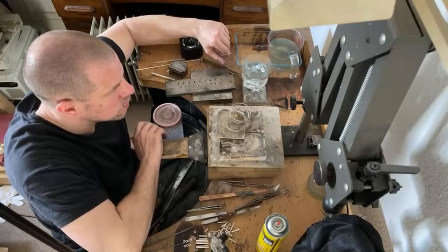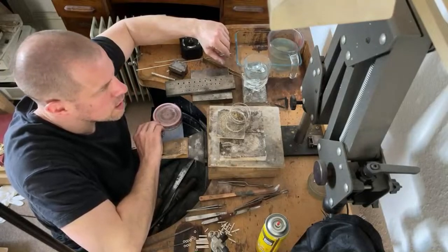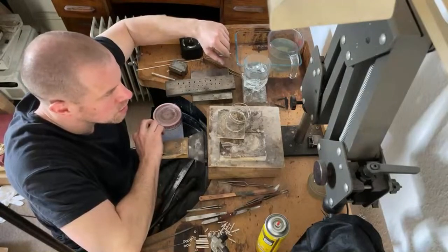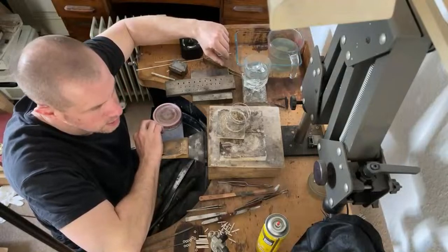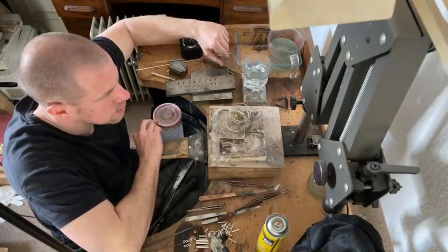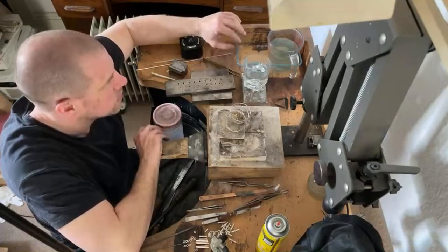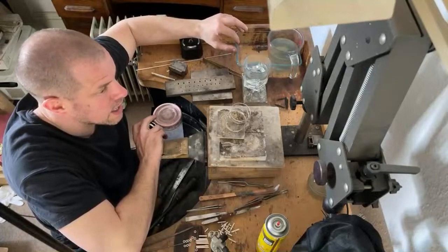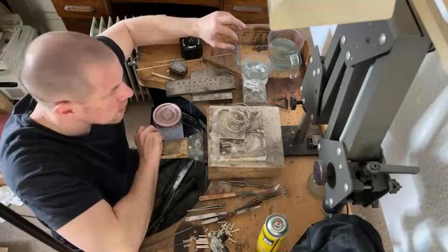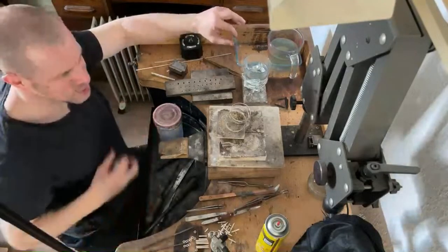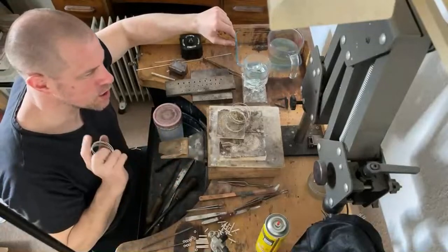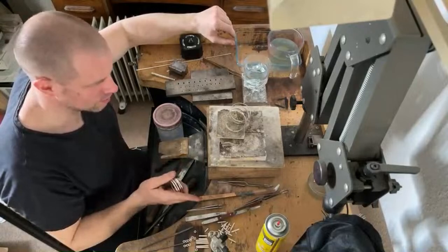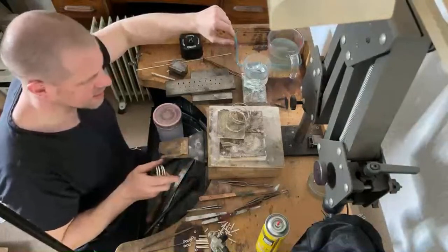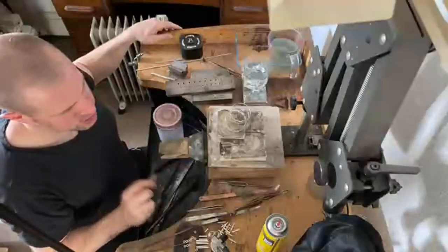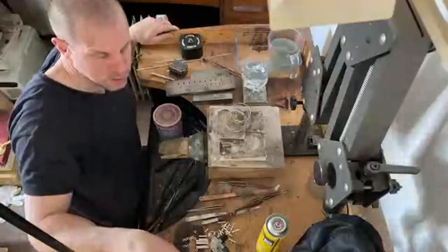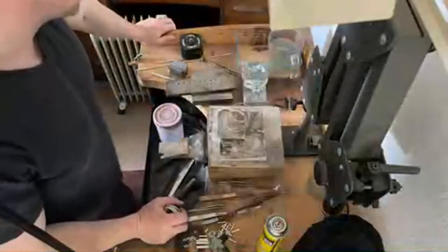But I think cooling it too slowly matters too. If you heat gold and silver, there is a way of really hardening them, harder than work hardening, by heat treating: getting it to annealing temperature, then cooling it really slowly. I think it's really hard to do, and I think that's what most people are actually doing, but they're getting it wrong. Two wrongs make a right. They're air cooling gold, which if done right would be rock hard, but luckily we're getting it wrong in that sense. The cooling speed is critical, and I think you need a furnace to do it properly. Doing it just in the air, it would be a pure fluke if you nailed it.